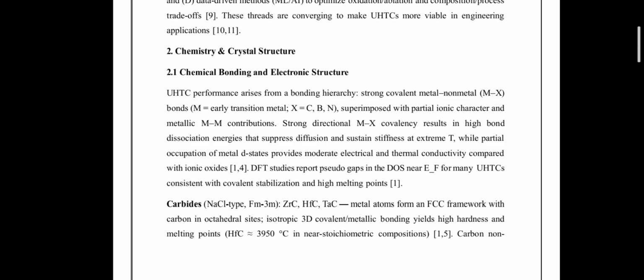This covalent bonding is supplemented by partial ionic character and metallic metal-metal interaction, creating a balance between stiffness and transport properties. The strong directional covalency suppresses atomic diffusion and maintains mechanical rigidity at extreme temperatures, while partial d-band occupation enables moderate electrical and thermal conductivity, unlike conventional oxide ceramics.